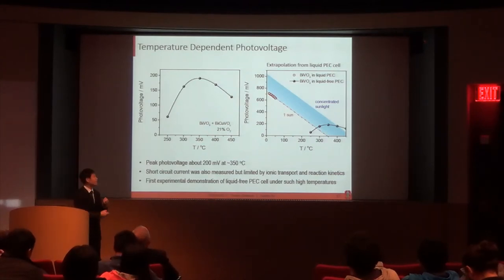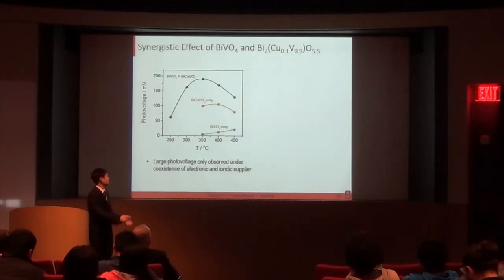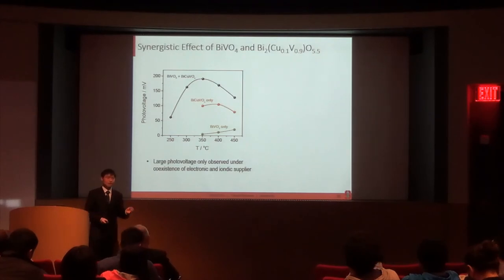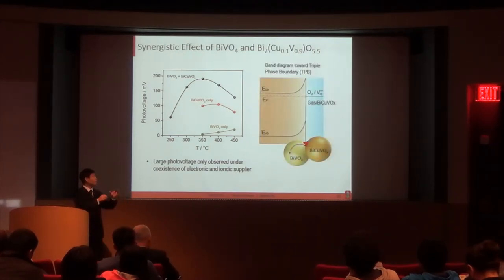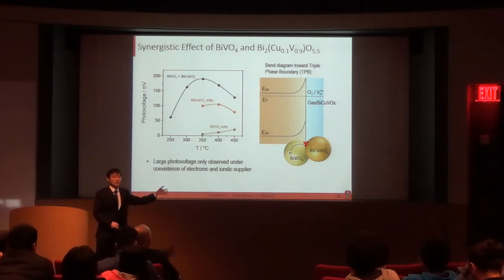So in order to understand this unusual behavior of the photovoltage, I first confirmed that such a large photovoltage can only be achieved with the coexistence of bismuth vanadate and bismuth copper vanadium oxide. So there's a synergistic effect between the semiconductor and the ionic conductor. So it is reasonable to rationalize a charge separation picture at the triple phase boundary. Here I show you a band diagram that shows the band bending within the semiconductor toward this triple phase boundary. So the redox level in this case is now determined by both the gas phase and the ionic conductor.